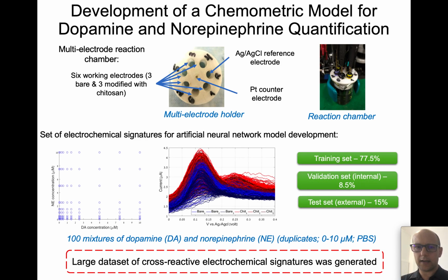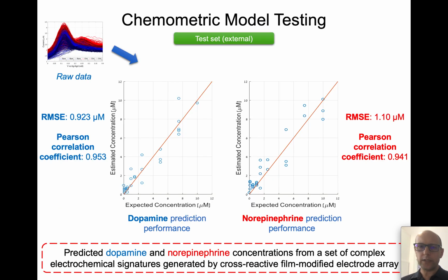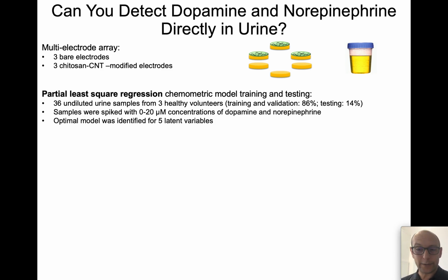So we tested 100 different mixtures of dopamine and norepinephrine in buffer. We divided them into training and testing sets, and we trained a chemometric model, an artificial neural network model, to recognize the fingerprint of dopamine and norepinephrine in mixtures. And the results show that we get a very good prediction of both dopamine and norepinephrine, with correlation coefficients of 0.95 and 0.94. So it gave us a good impression that we can use this approach to differentiate these overlapping signals.